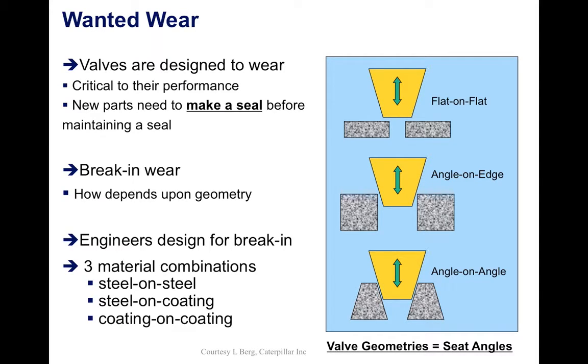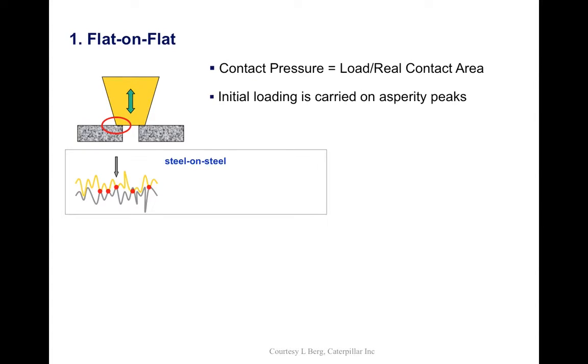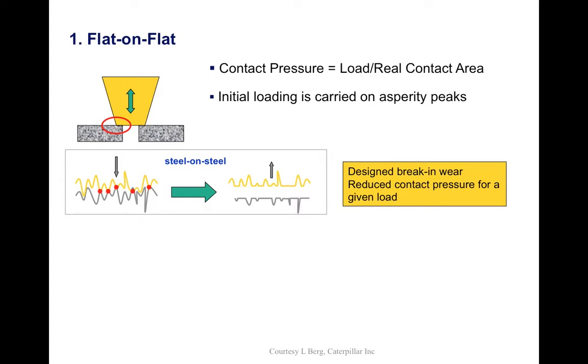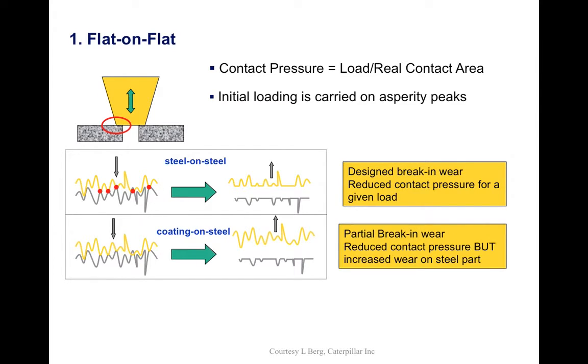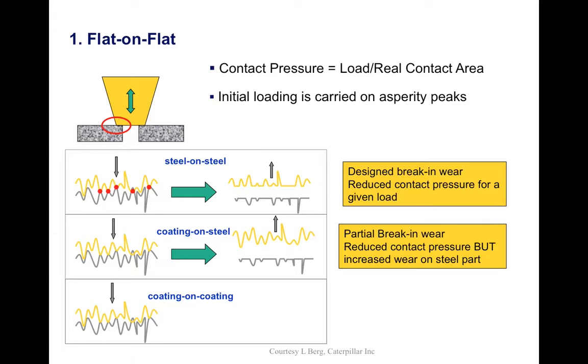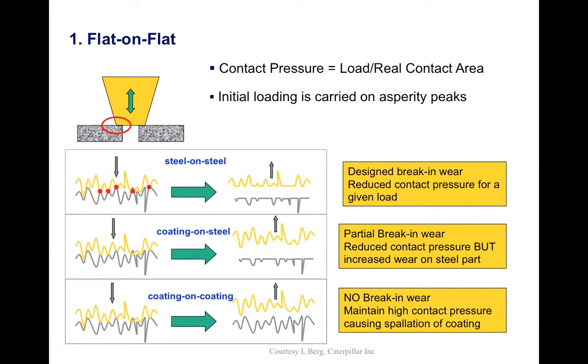And the engineers need to design for a steel on steel, a steel on coating, and a coating on coating. So you can begin to see this is extremely challenging. So they look at the deformation of the asperities, on steel on steel, steel on coating, and coating on coating. And coating on coating didn't work. Coating on coating gives them a maintenance of a surface which actually doesn't wear and actually leads to failure of the coating because the local pressures are too high.